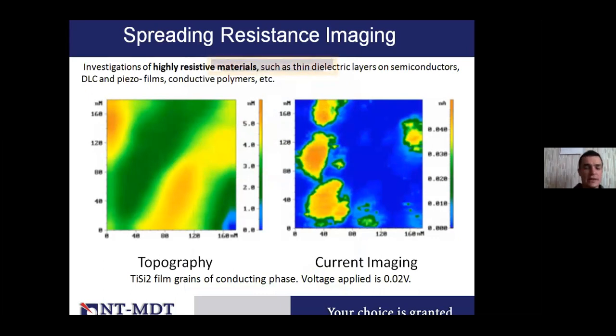As a result, we can see such images, for example, as you can see on the slide. This is a film, titanium silicon grains on the conductive phase. On the left, you can see just a topography with dimensions of below 200 nanometers. And on the right, you can see the current distribution of the same area during the same measurements. The voltage applied between tip and sample is just 20 millivolts. You can see that the two images do not correlate to each other. It means that from the topography, we cannot distinguish what these areas are, whether they are conductive or not. But from the current images, you can see clearly that these islands are more conductive because we got the current in this area at this level with the constant voltage. So this is a very good technique for material science to measure the conductivity.